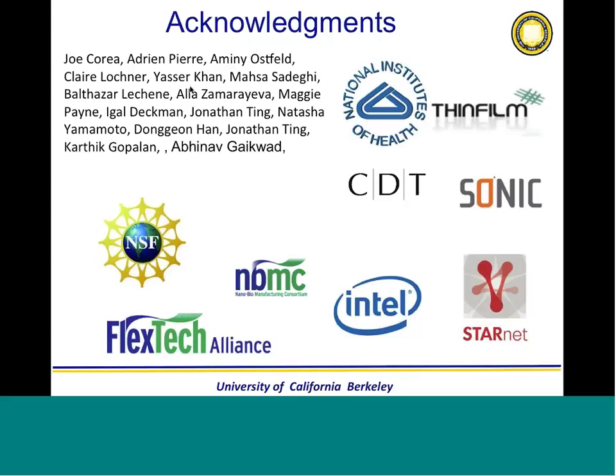I haven't done that type of accelerated testing, but we did do the measurement for 7 days without encapsulation. Because what you want is the ratio, and the devices that degrade the most are the OLEDs, because of the high current and they have a low work function material in the stack. And up to 7 days, we could still do the measurement. There was a little degradation, but you could still do the measurement. So all of a sudden, all these people that are trying to make OLED TVs are also interested in medical devices, because it's a completely different proposition.